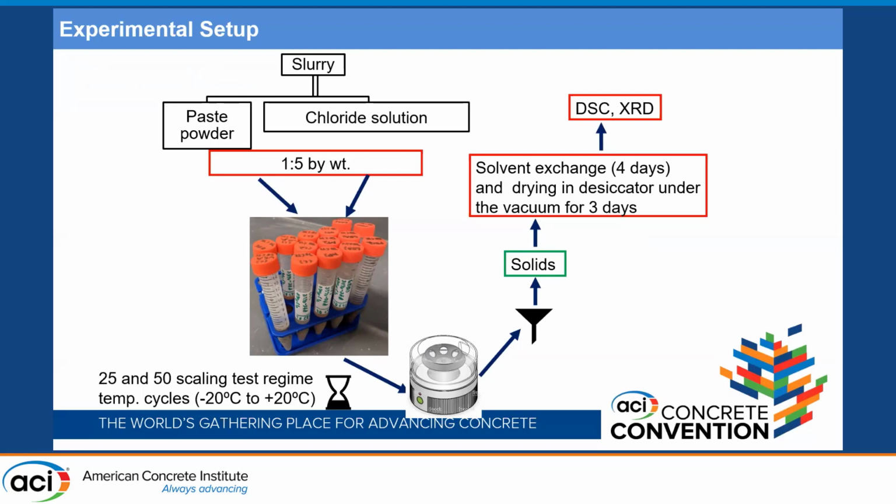After termination of the 25 and 50 scaling cycles, we centrifuged them and filtered the solids, triple washed with deionized water, and again removed the water with the solvent exchange method, vacuum dried, and then used differential scanning calorimetry and quantitative X-ray diffraction methods for analysis.